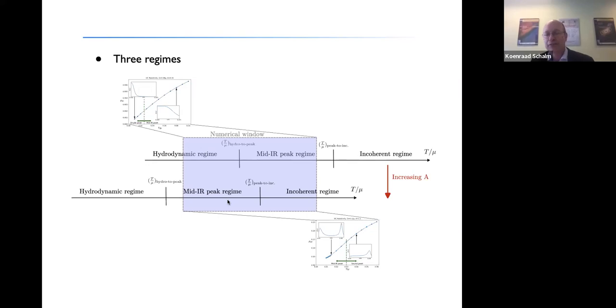Even though, in particular for the large A regime, there are very good physics reasons to believe that if I would be able to compute at lower temperature, I would get back into the hydrodynamic regime where I would still also have a linear in T resistivity. And then I would have an example where I should see a transition between three regimes in one model, even though the linear in T behavior of the resistivity stays the same. So this is a numerical aspect that unfortunately means we cannot give you one coherent picture. But as I go on and explain, I hope you realize that this is really the point of view to take.